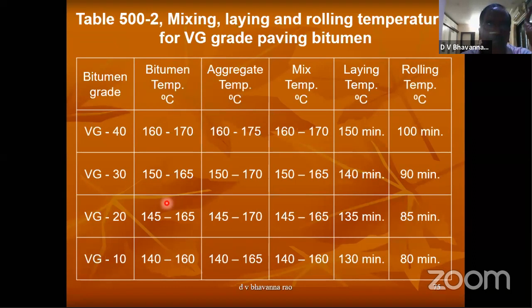We have to control the temperatures of bitumen, aggregates, mix temperature, laying temperature, and rolling temperature. Suppose we are adopting VG30, these are the temperature requirements, and the difference between the temperature of bitumen and aggregate shall not be more than 14 degrees. It is very important. And we have to complete the rolling before the mix reaches 90 degrees.